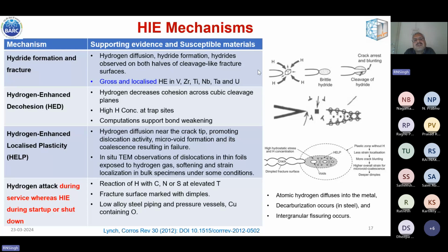So usually for steel, hydrogen embrittlement is not reported above, I think, 250 degrees Celsius or so. Yes, right. Because at lower temperature only hydrogen embrittlement is observed. At very low temperature, you can imagine that hardly any hydrogen will be present in solution, so that's why its embrittlement effect is not there. As you go to higher temperature, some hydrogen will be in solution, and if it is causing decohesion, then I think the embrittlement effect will be observed. As you go to higher and higher temperature, probably this decohesion effect is not there.